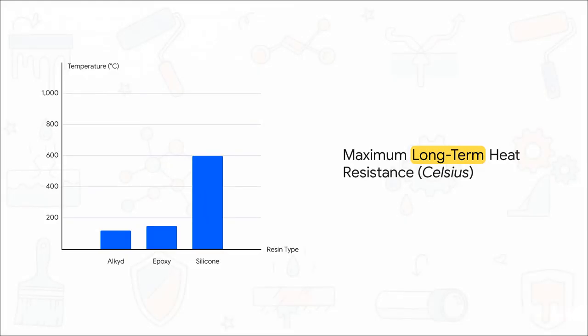Just look at this staggering leap in temperature tolerance. I mean, alkyd taps out around 120 degrees Celsius. Even our heavyweight epoxy starts breaking down at 150. But silicone sits comfortably at 600 degrees Celsius, long term. And what's truly mind-blowing is how it behaves as it heats up. Traditional resins melt or turn to ash. Silicone actually undergoes further condensation at high heat. It doesn't degrade, it actually gets harder and more densely cross-linked the hotter it gets. No way around it, that is just cool chemistry.